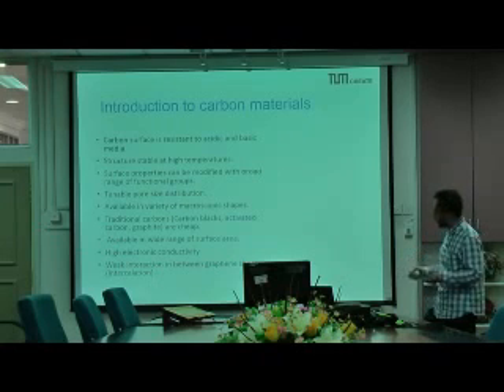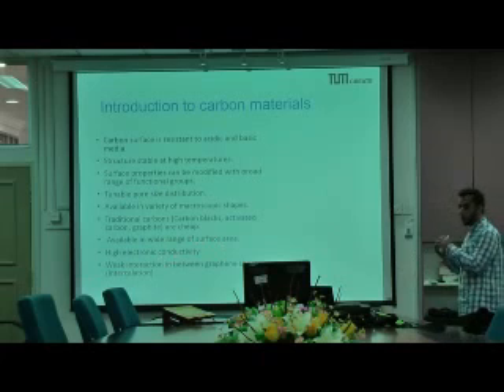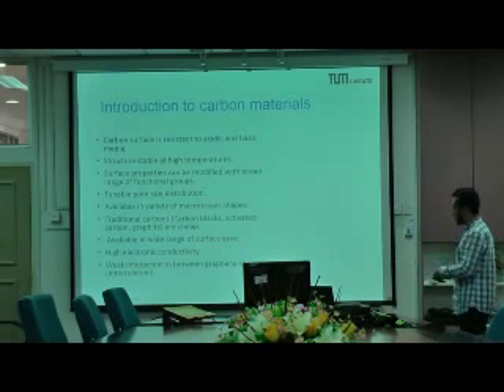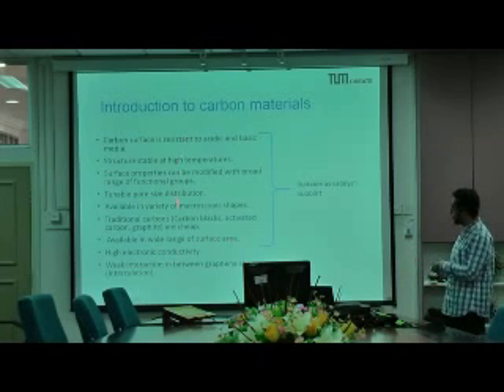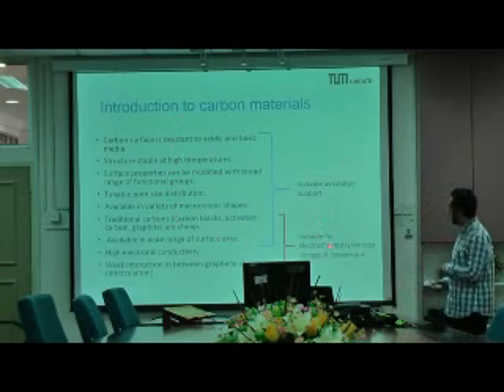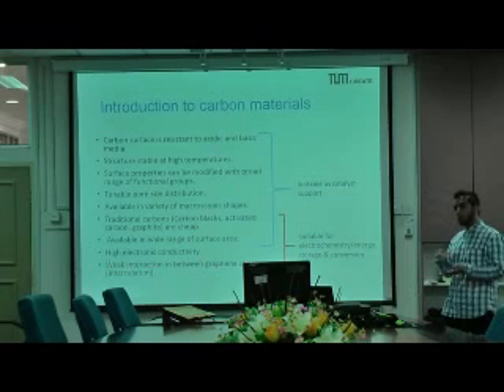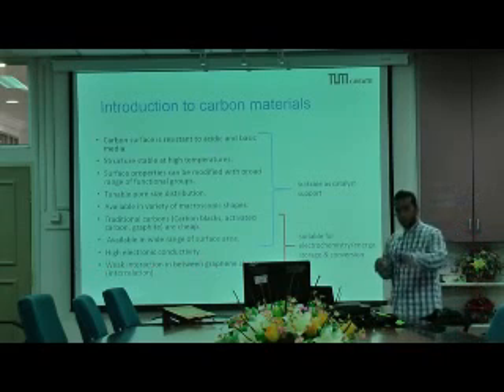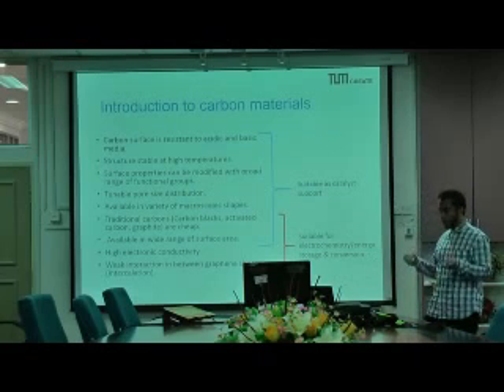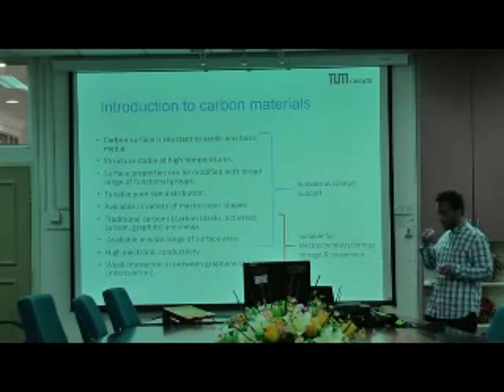You can prepare carbon materials up to 3,000 square meters per gram, which is a very big area, and it has a high internal conductivity. In fact, in all batteries, you will find carbon inside due to these properties. So these parameters are exploited for use as catalyst material, and for electrochemistry and storage. One thing to note, as I will explain in my talk, is the weak interaction between graphene layers, the one we normally use in our pencils. This is exploited in lithium ion batteries to have lithium ions intercalated between the layers.